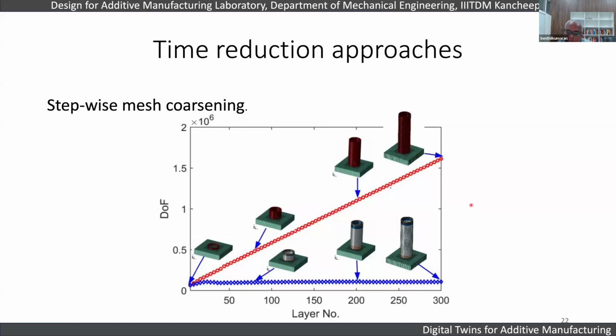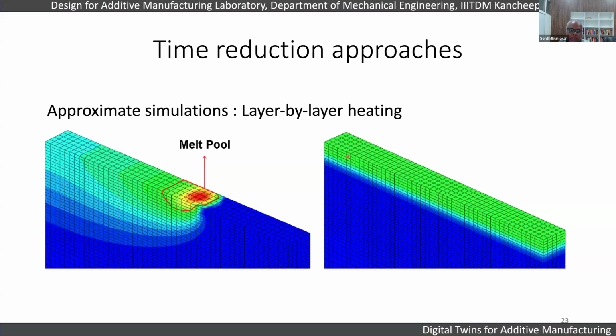And many people try to also not do the scanning for each individual track path, but assume each layer is manufactured in one go. This is typically what we call layer by layer heating. So instead of simulating the laser movement as a moving heat source problem, people have solved this problem by assuming each layer to be heated and then formed. They had a very approximated simulation wherein the entire layer can be simulated in one go.